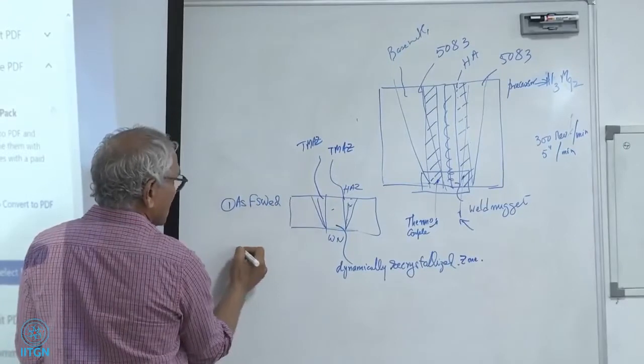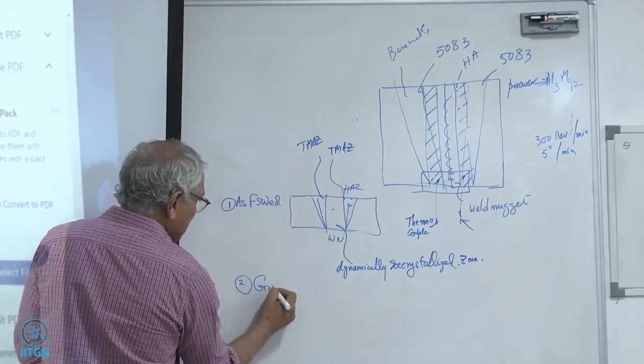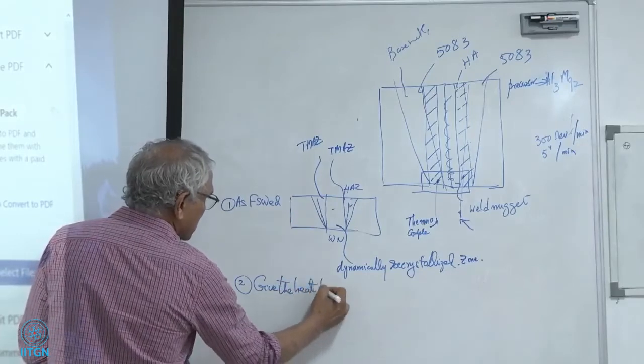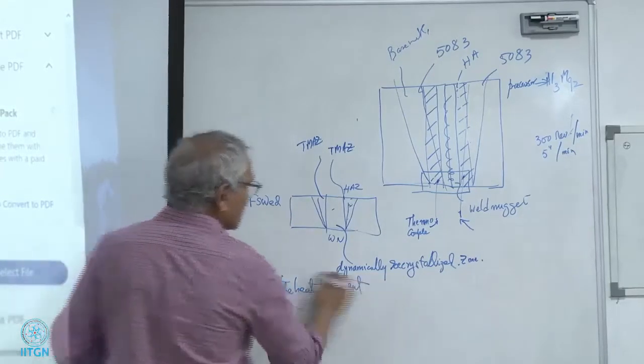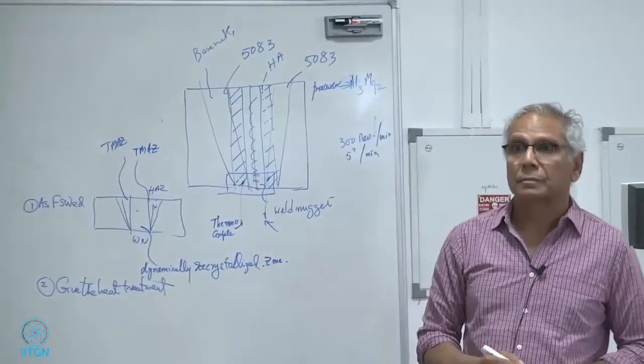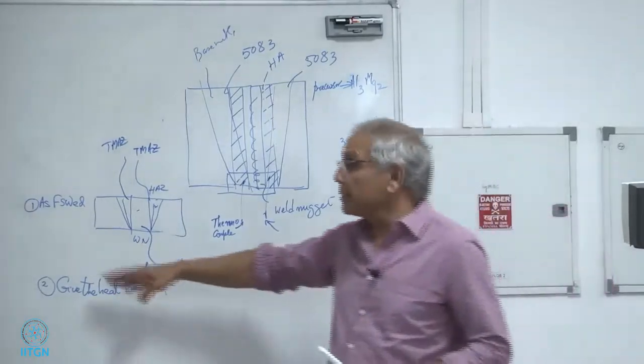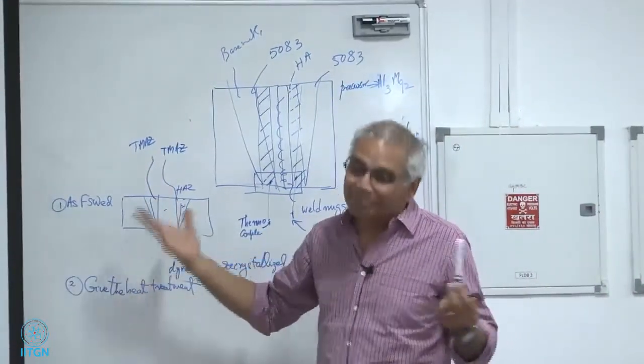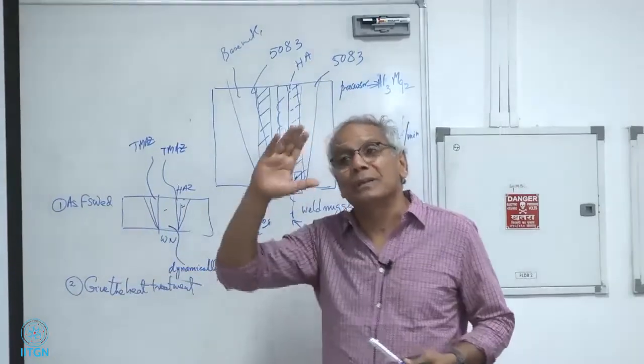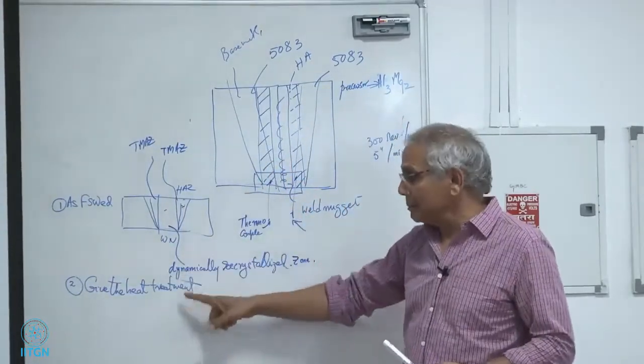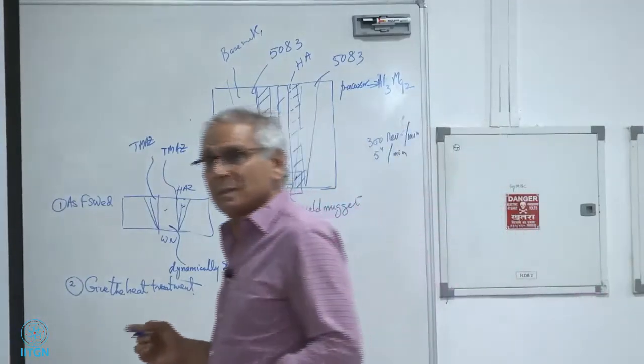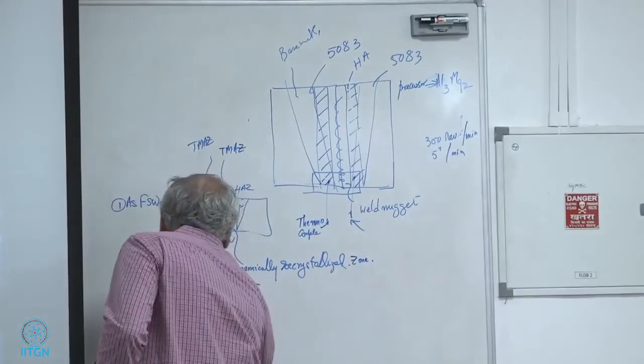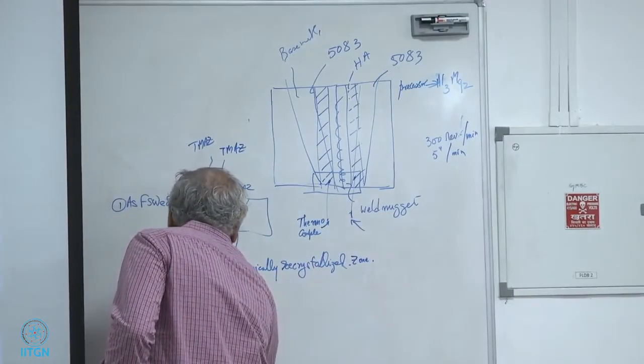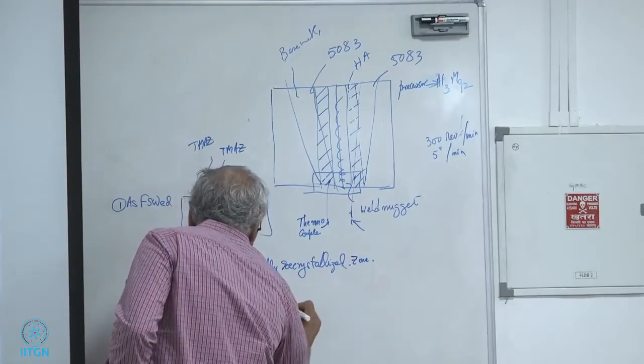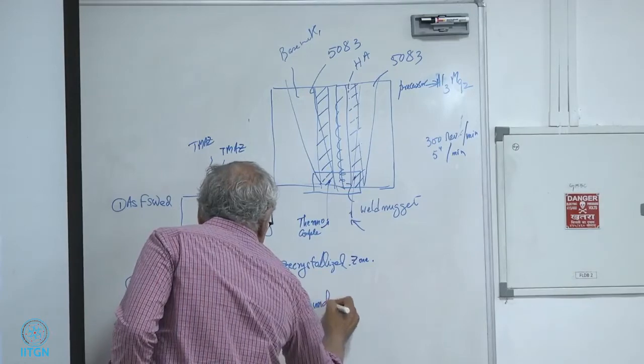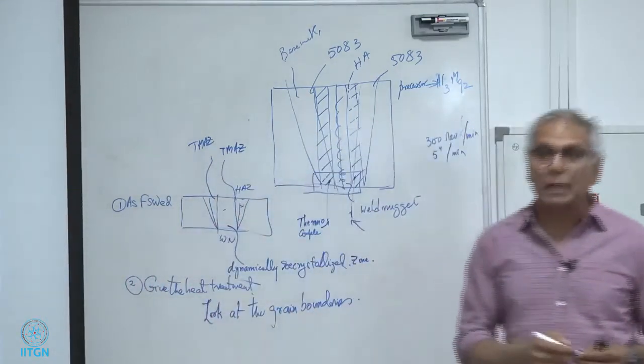As friction stir welded. So number 2, give the heat treatment. Actually, before you give the heat treatment, I don't think you have a residual stress measurement. Then you can choose the heat treatment so that you can relieve the residual stresses, but at the same time, they will be forming grain boundary precipitates in this heat treatment. When I say look at the grain boundaries, I mean image the grain boundaries.